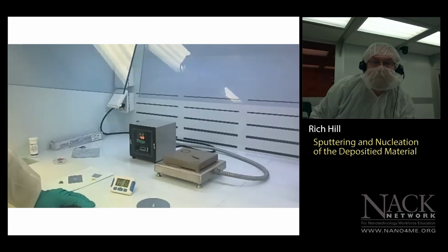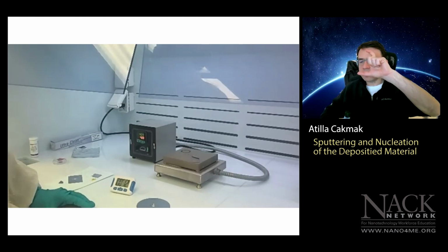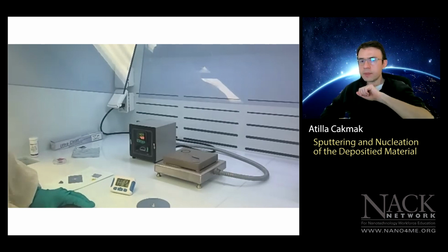Yep, I can see that visually from my end. I can see it changing color already. Yeah, we have the nucleation taking place. So thermodynamically, the gold is migrating and driving to become more uniform, but smaller in size. Its aspect ratio, what I mean is its height is getting larger with respect to its width, and that will change its light interaction property. So we will see different color getting reflected.